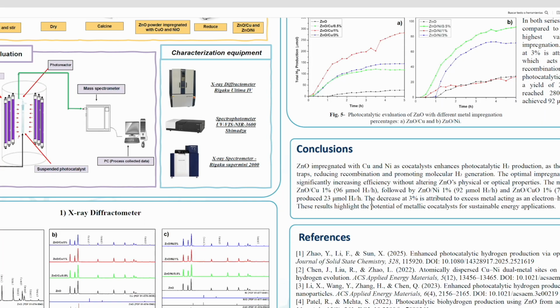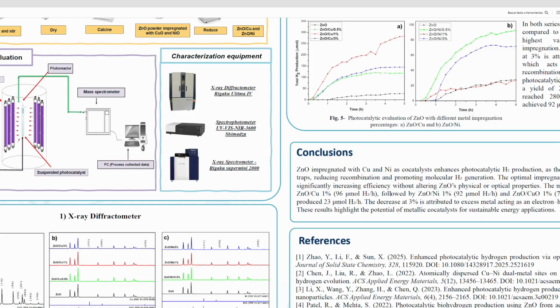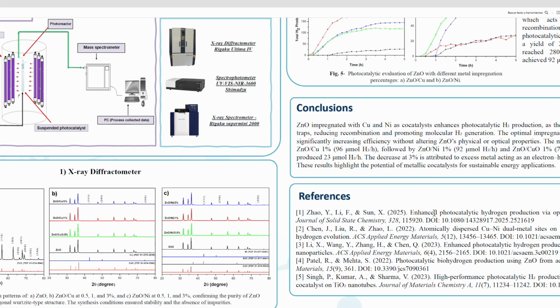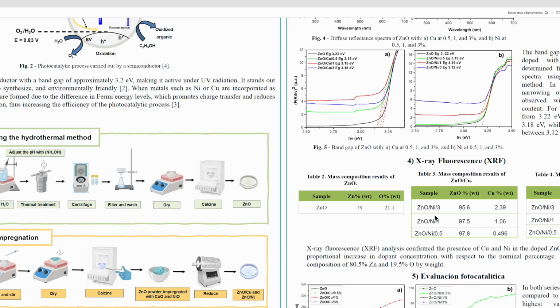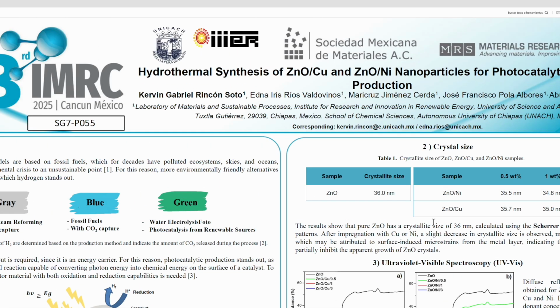So the conclusions are that we have obtained a material that generates hydrogen, and that by adding small percentages of nickel and copper at 0.5, 1, and 3%, the efficiency is improved, with the most favorable results at 1%. For this copper material at 1%, we obtained 96 micromoles per hour, and for the zinc nickel oxide, we also obtained very similar results. And for pure zinc oxide, 70 micromoles. So it's a quite acceptable conclusion, and that would be all from me. Thank you very much for your attention.